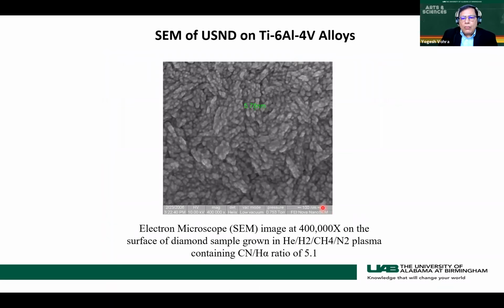So how small can you go with this? There is a term used in the literature called ultra smooth nanocrystalline diamond, USND, which has been deposited on this aerospace alloy, titanium 6, aluminum 4, vanadium. And the smallest size you can go to is about 6 nanometers.